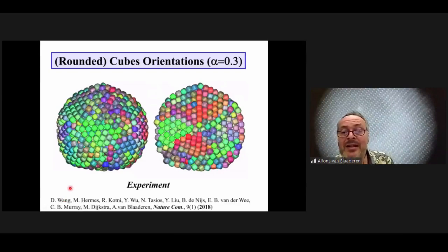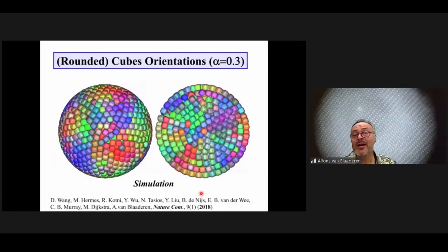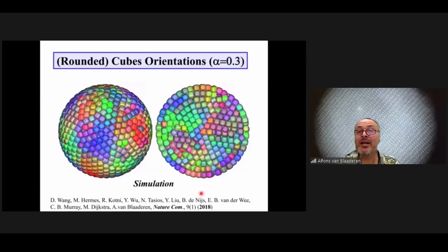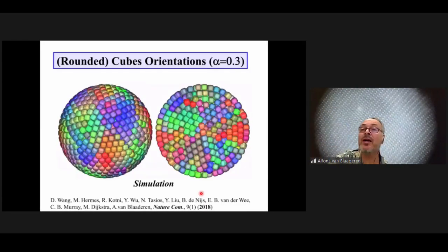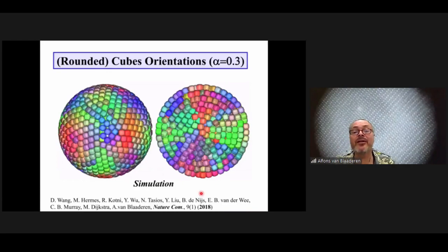And what you can see is that the same particles around a central particle have the same color. So they're still strongly rotationally correlated, but only to their next neighbors. The correlation function drops off quite fast. But for getting directed attachment in 3D, this is an important property, because the icosahedral symmetry is completely different than the cubic symmetry of their more sharp cubes. And we found exactly the same in the simulations, as long as we also took the ligand layer into account in the shape parameter as well.